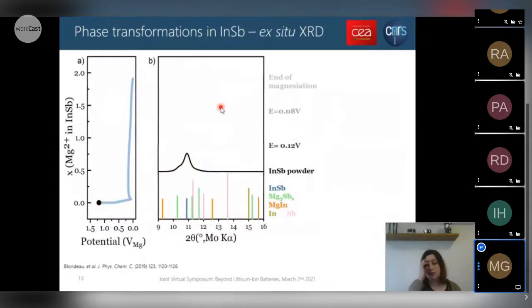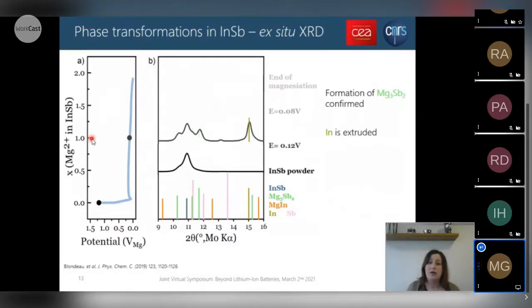To reveal the phases formed, we performed ex situ X-ray diffraction at different steps of the magnesiation of InSb. So we start before cycling, and we have the characteristic signal corresponding to the InSb compound. Upon magnesiation, when we insert close to 1 Mg2+ in the structure, we have, as expected, formation of Mg3Sb2. And we also see that some metallic indium is extruded from the structure, which is in fact similar to what has been seen before in the literature for the InSb reactivity with lithium.